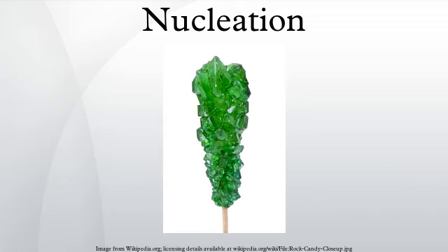Experiments on the nucleation of crystals. It is typically difficult to experimentally study nucleation. The nucleus is microscopic, so the nucleus is too small to be directly observed. In large liquid volumes there are typically multiple nucleation events, and it is difficult to disentangle the effects of nucleation from those of growth of the nucleated phase. These problems can be overcome by working with small droplets. As nucleation is stochastic, many droplets are needed so that statistics for the nucleation events can be obtained.